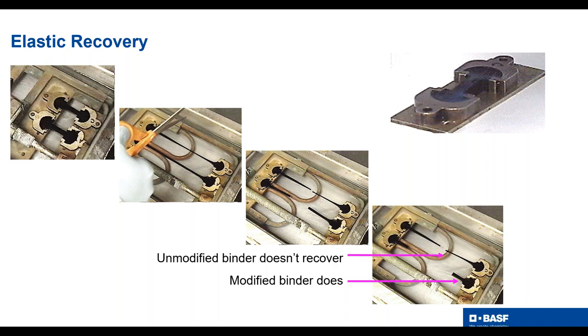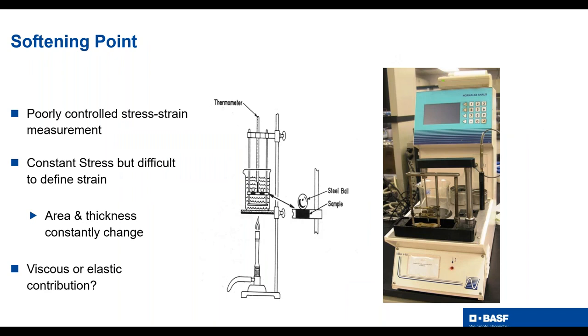The other test is softening point. We have a picture of ours in the lab. We have an automatic softening point tester that we use. Some people call this, it's not a very good stress strain measurement. You have the steel ball on it. You heat up the water. There can be other things if your softening point is high, but usually water. And the steel ball, you measure when it drops down and touches the bottom with the asphalt sample. So it's a kind of unique test to run, but it is run on a lot of microsurfacing applications. And that's one of the reasons that I wanted to show you a video clip of that as well.